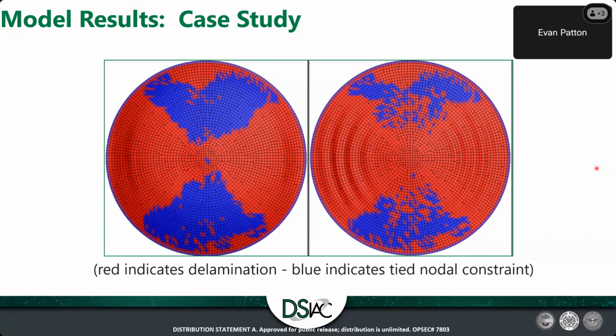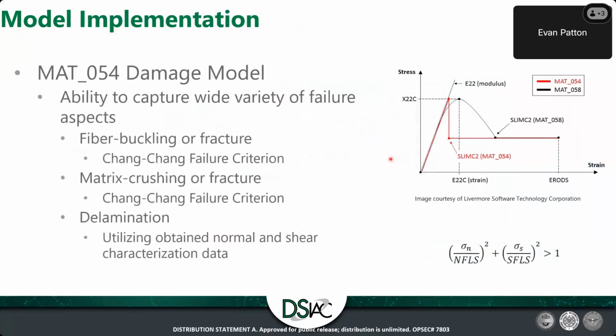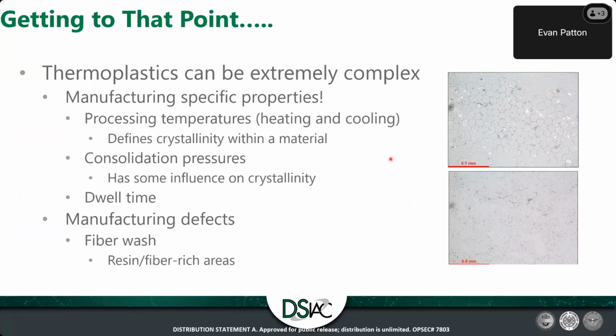I did have some microscopy images here. Again, there was no void content assessment, but we looked at the microscope images and we were pretty happy with the consolidation results, seeing that there wasn't as much void, if any, within the material. So we just left it at that because we were, again, just characterizing the material as manufactured.